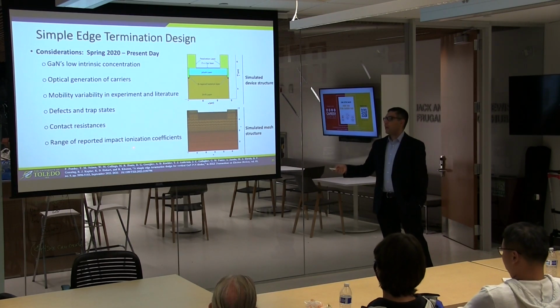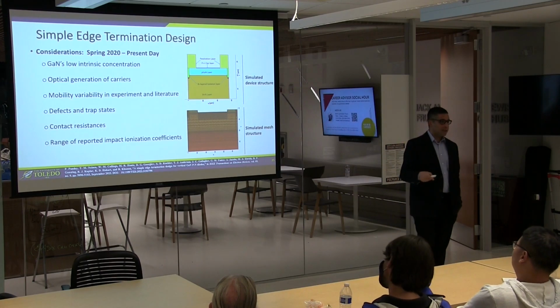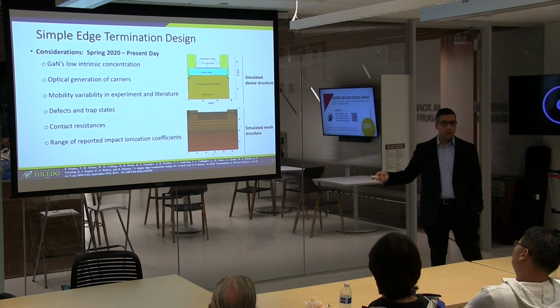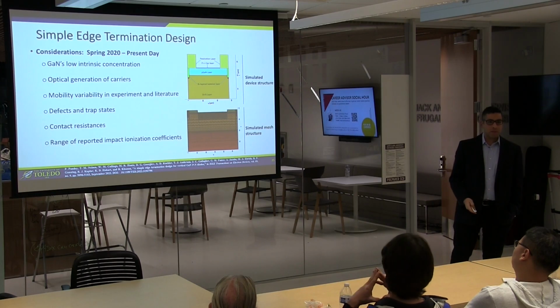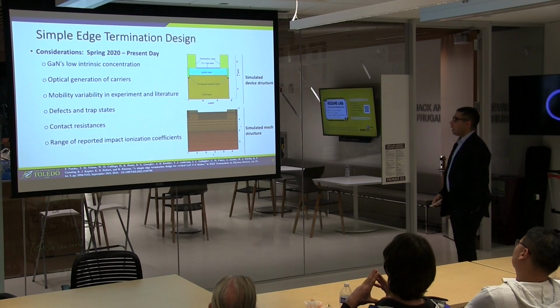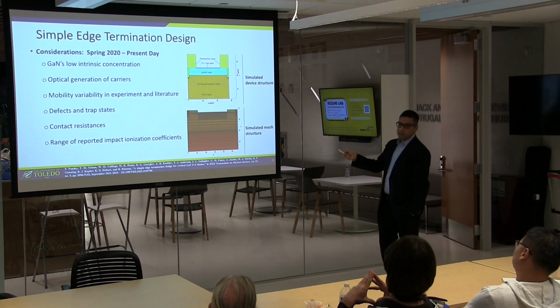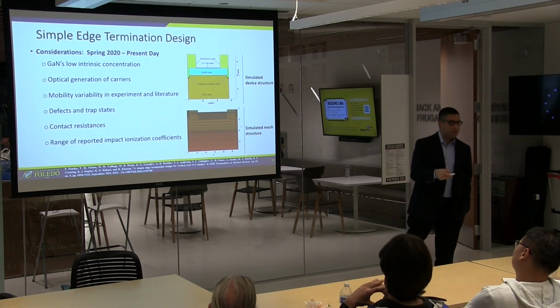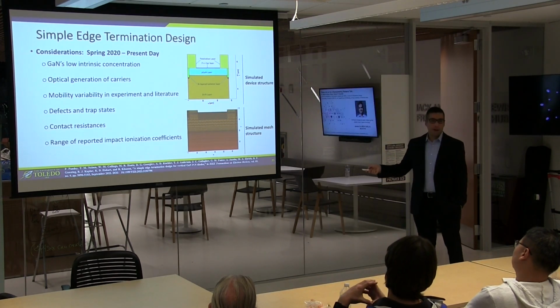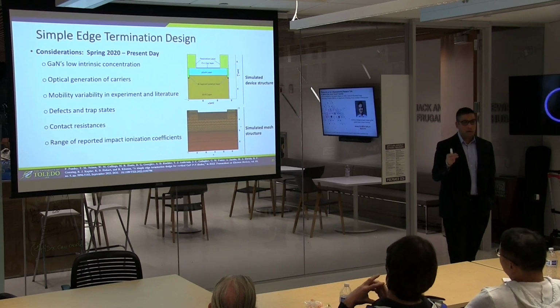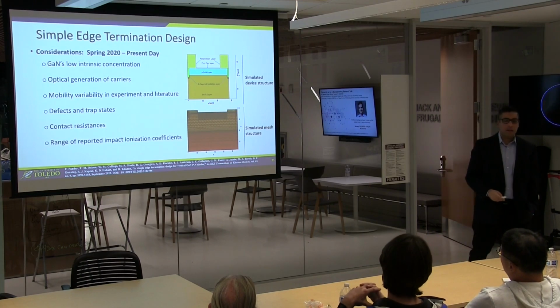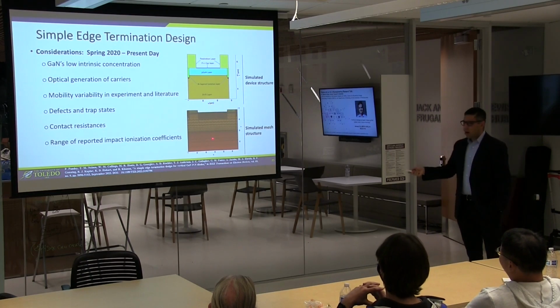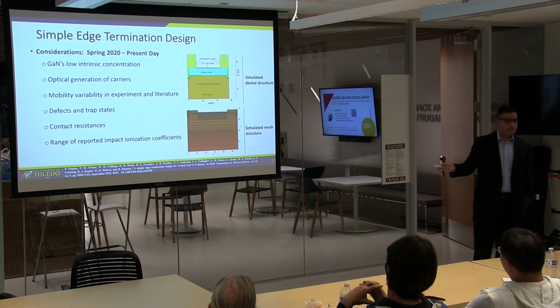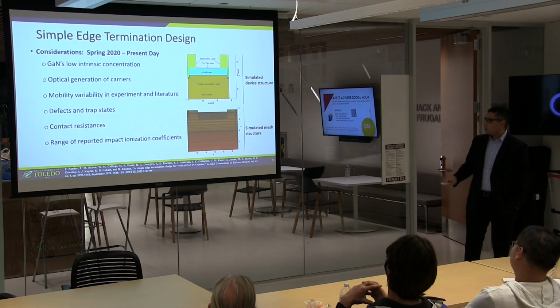When we measure breakdown, we're basically wanting to see that ionization integral go to 1. We don't actually measure breakdown. We just look at the ionization integral until it goes to 1. So this is our simulated device structure of that same device that you saw on the previous slide. This is the mesh structure of that device. And of course, when you do finite element modeling, you have to have a good meshing. There are something like 100 to 150,000 elements in this structure right here.